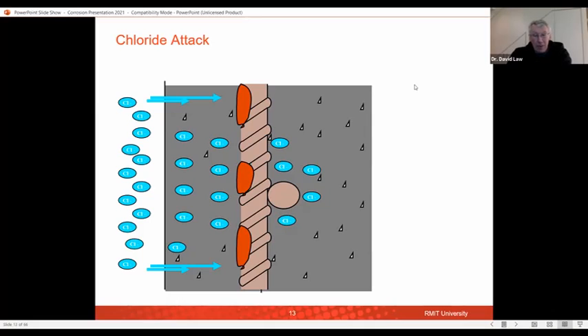And thus, the protection that you've got is your concrete. You've got the distance, the cover depth, you've got the density or the compaction, the porosity that you've got in that matrix as well, because it will diffuse through the interconnected pores and the pore water. So those are how you can try to design out chloride attack. But when the chloride ions come in, they will then reach a concentration at this steel rebar that will initiate corrosion.